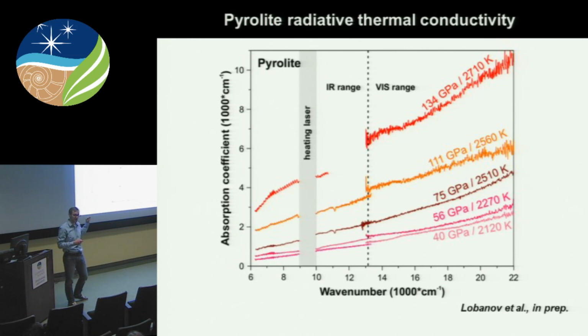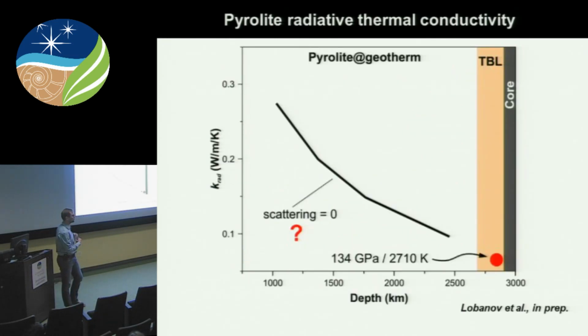So the bottom four spectra approximate the PT conditions that are met on the Earth's geotherm. So these are, in a way, ideal input information that we want to use in order to constrain radiative conductivity as a function of depth. The red spectrum, however, that was taken at 134 GPa, was taken at slightly lower temperature than we would expect for the core-mantle boundary.